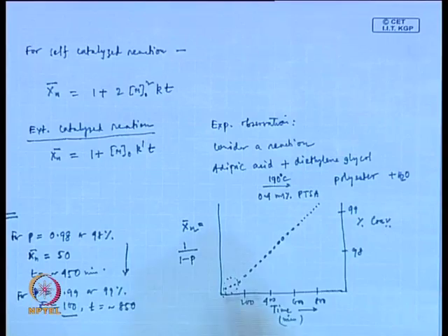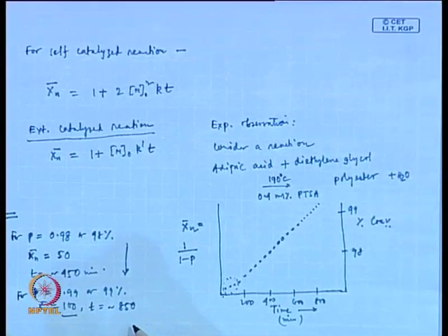Now, because you have to keep this reaction for a longer time, sometimes that poses some difficulties in terms of stability of the ingredients, the chemical species present. As we have seen, this is typically done at higher temperature, which means that if we keep this for so long, there is a possibility that the polymeric species might degrade and form colored species, which is not desired.